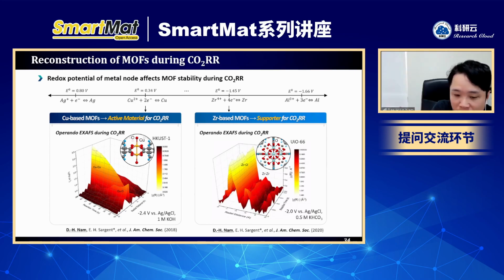Oh yeah, thanks for raising a very important topic about my CO2R catalyst. You pointed out very important things. Because we applied a negative potential for CO2 reduction, this can reduce not only the CO2 but also the metal ions on the catalyst surface. That is the reason why we could see this kind of graph according to time. So compared to zirconium and copper, in this case, copper is reduced.